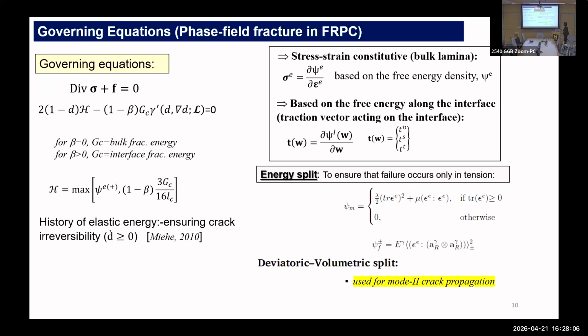So here we have done quite a bit of manipulation. I'm not going into the detail because you can find it in our recent papers. But again, reminding you that this 1 minus beta term basically takes care of this interactive fracture phenomenon. So if the crack traverses from bulk to the interface and then interface to the bulk again, then this term is going to dictate how the fracture energy will change as the crack path changes.